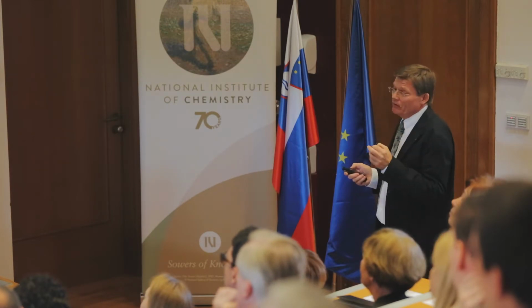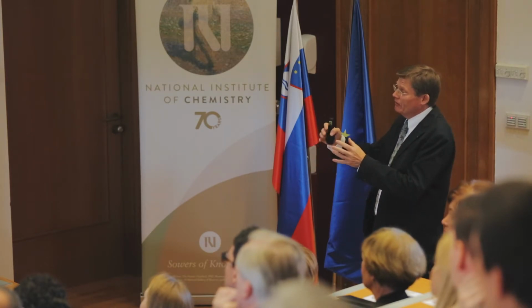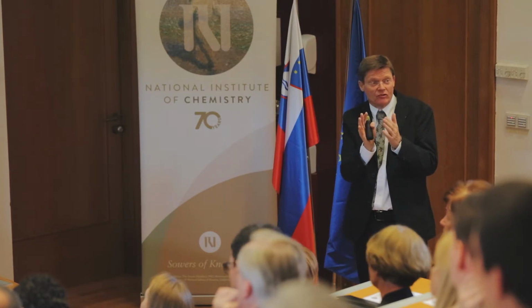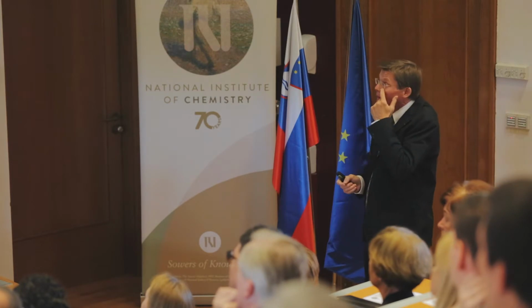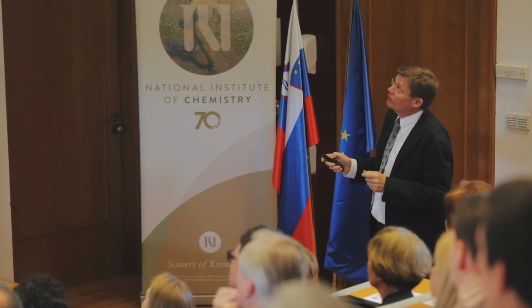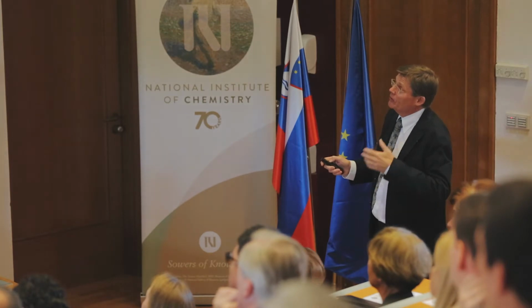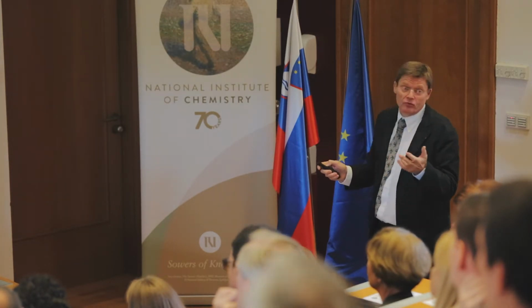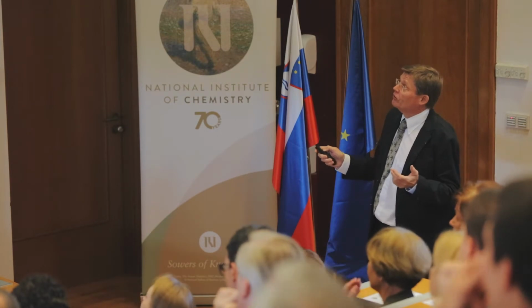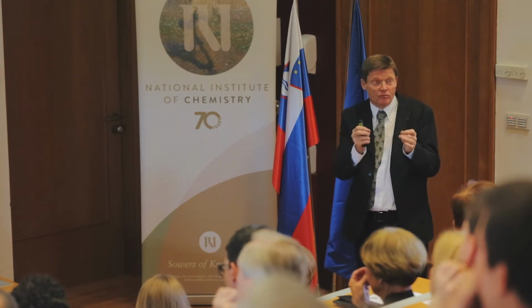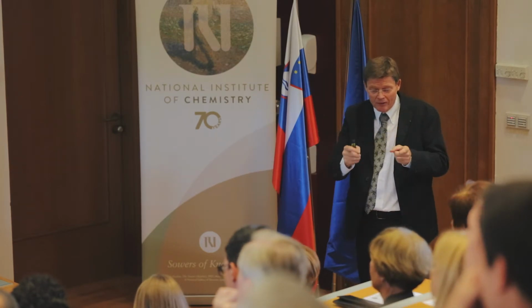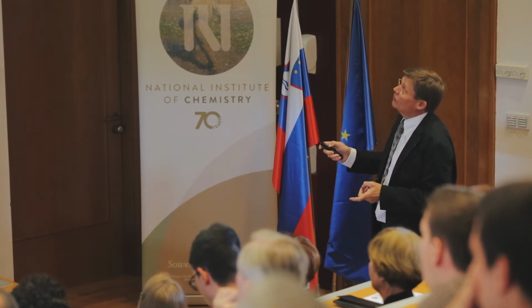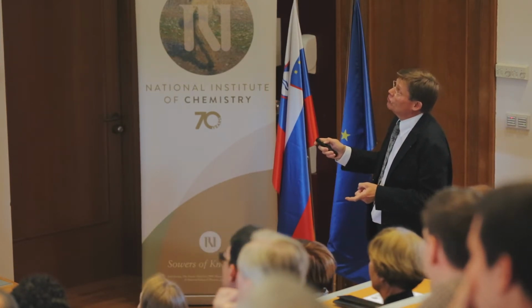The third example. Now, the experiment is very simple. We do only chemistry. We take our oxide, we change the oxygen partial pressure, and we look at how the stoichiometry inside changes. We understand this very well. The time behavior is characterized by chemical diffusion. We know what is in the chemical diffusion. You have contributions of ions and electrons, because you need both. Oxygen goes in, you need ions and electrons to move electroneutrally inside. So you have ionic and electronic contributions, ionic and electronic concentrations.